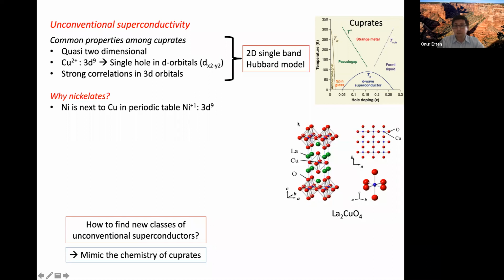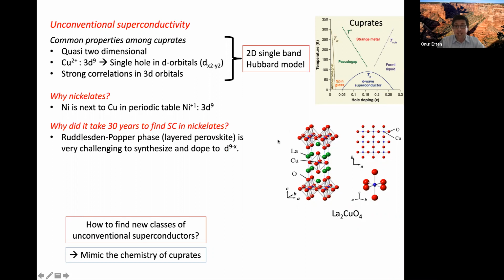If you can make the same structure with nickel 1+, according to everything I discussed, it should be a superconductor. Then this raises the question: why did it take 30 years to find superconductivity in nickelates, if it is that simple? The answer is that this layered perovskite structure, the Ruddlesden-Popper phase in nickelates, turns out to be extremely challenging to synthesize and dope, because you don't only want to make the parent compound, you want to be able to dope it.